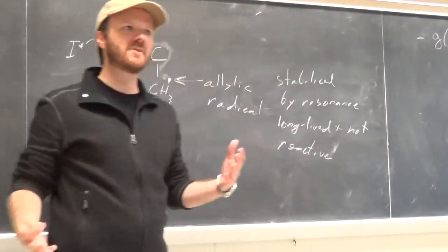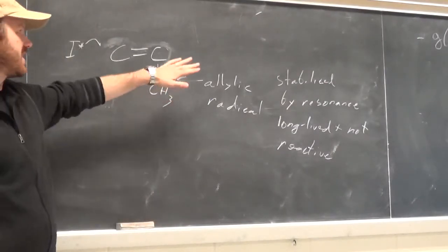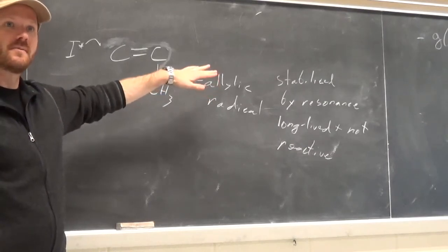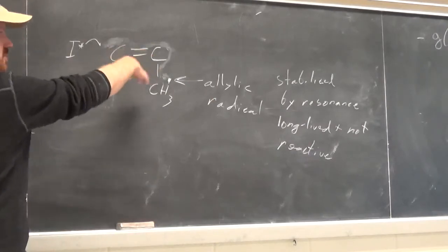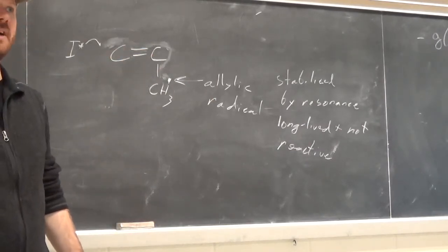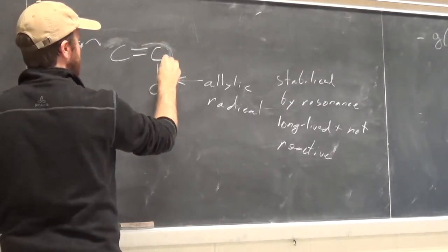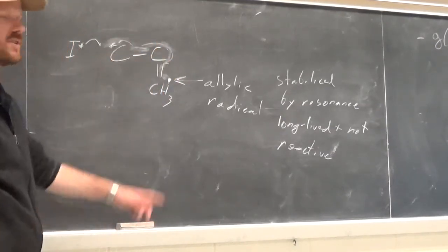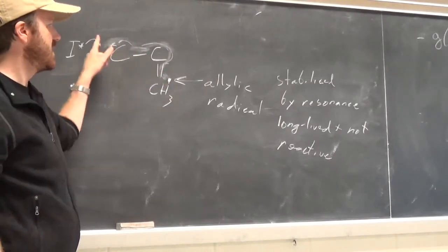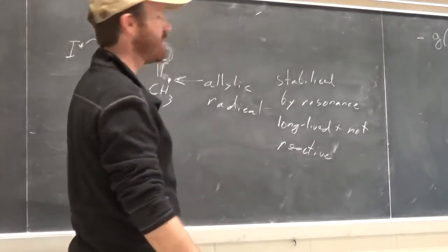And so it's a little confusing because benzylic radicals in styrene propagate no problem, right? But it turns out that allylic radicals are even more resonance stabilized than benzylic radicals. And so that's why these allylic radicals or polypropylene can't be made using free radical methods because of this resonance. So you can draw this resonance structure right here, or you can go back and forth. And so because this radical is delocalized in 2 places, it's not going to react. So that's just a special case that you should probably know.